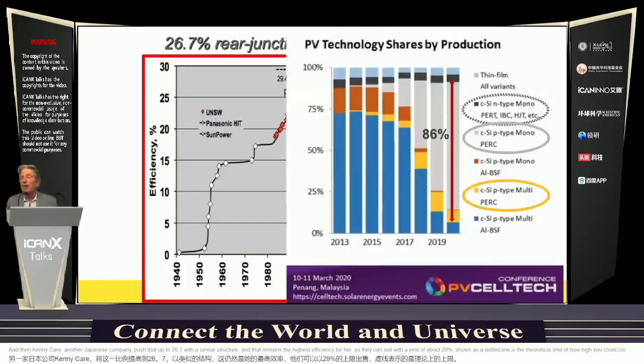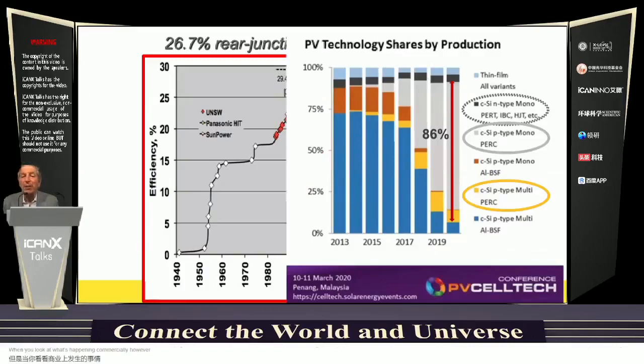When you look at what's happening commercially, however, that PERC structure that I invented way back in 1983 has taken over the market over the last few years. So in 2013, the beginning of this graph here, most of the technology is the blue and brown region, which was that aluminium back surface field technology that was developed back in 1974 that had dominated production, as you can see. But then you see little bits of yellow and grey creeping in and then growing very rapidly.